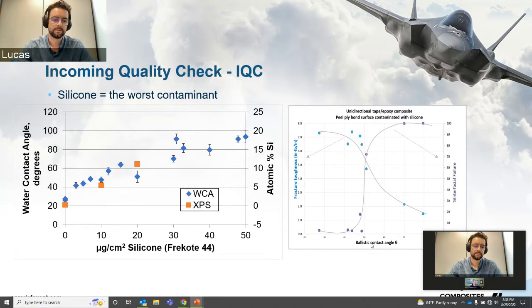Fracture toughness decreases, and the percent interfacial failure increases, and there's an inflection point right at about 50 degrees in contact angle. So below 50, things are working pretty well in general, though you can see kind of in the 40s things start changing. Above 50, things really start falling apart. And this is pretty common for a lot of applications. The range will be slightly different, maybe that cutoff point is a little bit different, but really, really good rule of thumb.